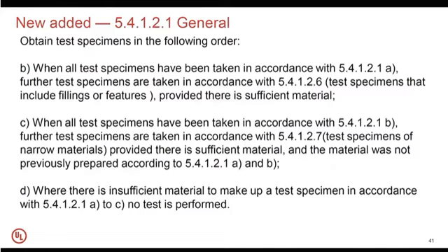prepared according to 5.4.1.2.1a and b. And the point D says that when there is insufficient material to make up a test specimen in accordance to the point A to C, so the previous points, no test can be performed. So in this way, there is sufficient information to be aligned in the sample preparation, which is for sure a critical stage of this kind of testing.